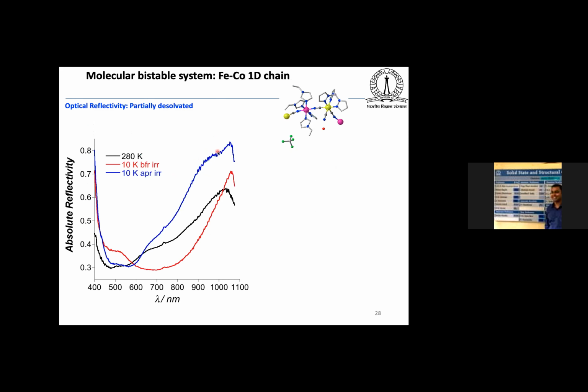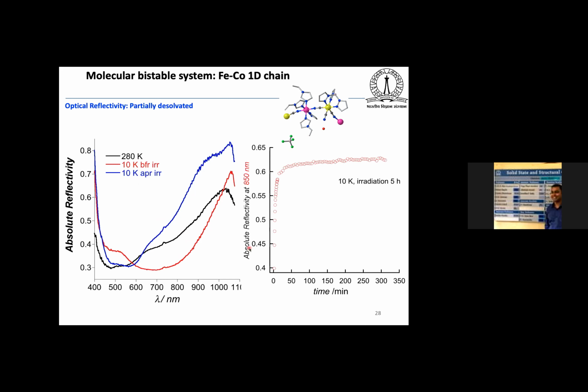And then what we have done, we have performed optical reflectivity, and now you can see here this partially dissolved system, and we have got the structure also. What we have observed is that here we have the water molecule, and the acetonitrile molecule is no longer there in the crystal structure, and this molecule is also showing photoactivity. You can see the reflectivity curve at 280 Kelvin and 10 Kelvin before and after irradiation, there is a huge change in the optical reflectivity curve, particularly in this region, and also in the 800 nanometer region and the 500 nanometer region. And also we have observed that using white light at 10 Kelvin, we can irradiate the sample and get the saturated value at approximately